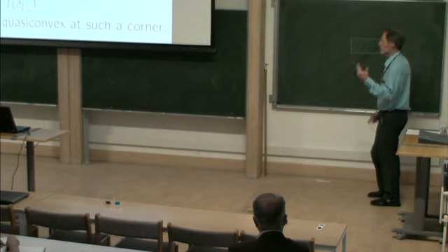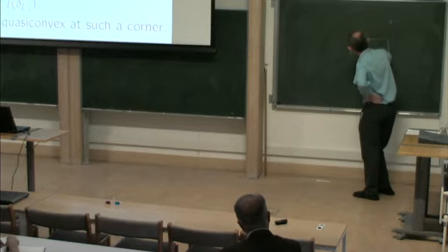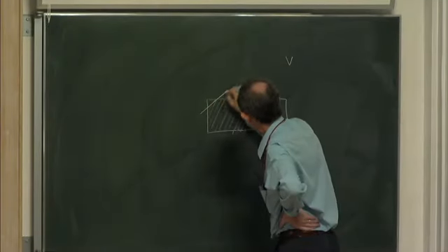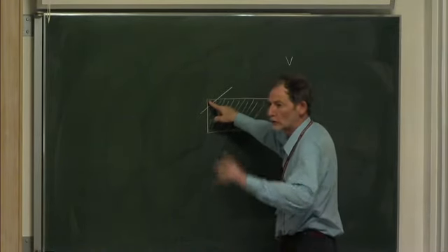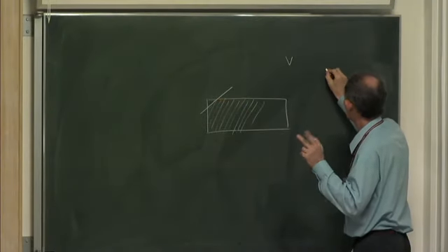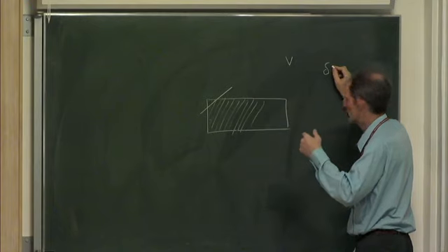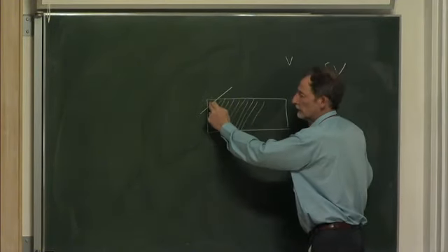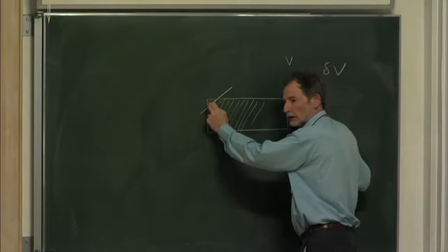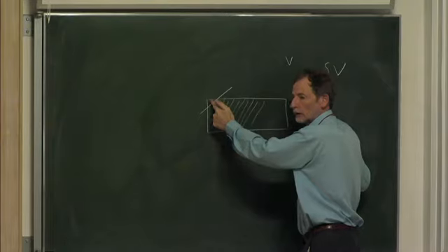laminate, right? Then what would you need to do to introduce a volume V of austenite? So the natural thing to do would be to bring in an austenite-martensite interface from here. Now, when you do that, you gain energy delta, which is the difference between the austenite and the martensite, times the volume V. But you also gain the interfacial energy from these interfaces, which are now no longer here.